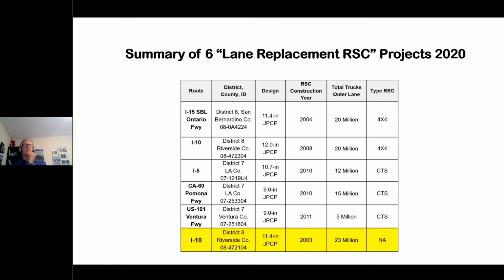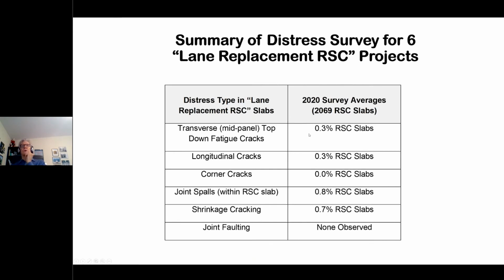Here are the projects, the 6, each row here is an individual section. You can see I-15, I-10, I-5 all the way down. And the yellow one is the one I just showed you. We're not quite sure what the RSC manufacturer is on that, but it was the oldest and heaviest traffic. So we definitely wanted to include that one. Okay, here are the results now from 2,000 slabs. And what's most interesting, transverse cracks, 0.3%. That's a very, very small number of fatigue cracking. And as you scan down, you see almost no longitudinal, corners, faulting, shrinkage, very little, all less than 1%.